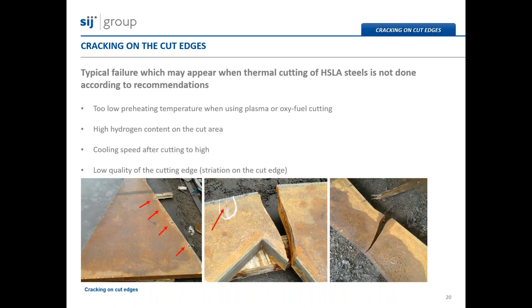It is typically detected when we have a combination of the following factors. The first one is too low preheating temperature when using the thermal cutting process. The second one is high hydrogen content in the area close to the cut line, like when we have wet plates which were stored outside the workshop. The third one is high cooling speed of the part after cutting. And the last one, low quality of the cut edge, which was already discussed before.